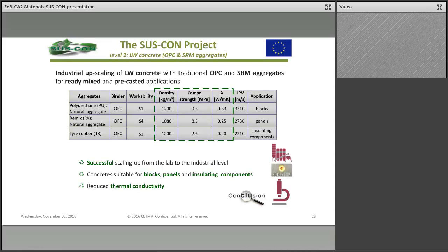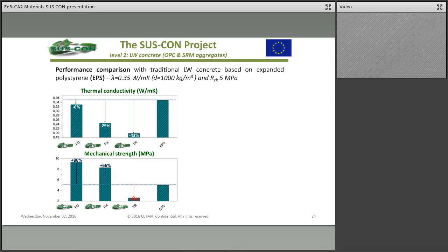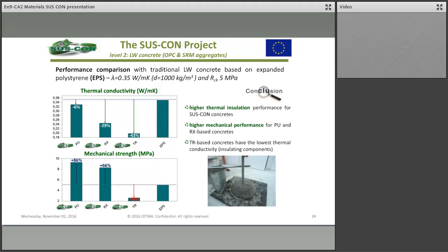In order to evaluate how good the performances of our lightweight concrete with secondary raw materials were, a performance comparison with traditional lightweight concrete based on expanded polystyrene was performed. And as you can see in this picture, lightweight concrete with secondary raw material aggregates resulted in higher thermal insulation properties up to 43%, and mechanical performances up to 86% for a concrete based on polyurethane and mixed plastic scrap.